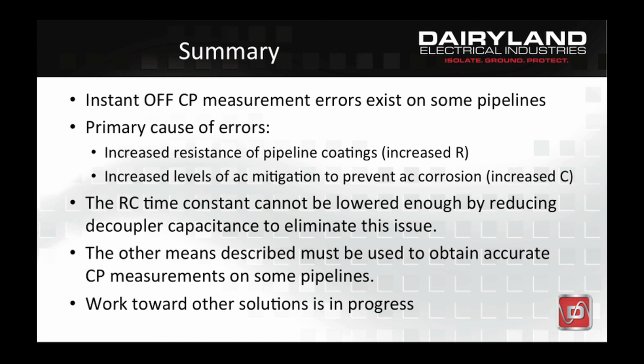It is now known that instant off potential measurement errors exist on some decoupled pipelines, and the reasons for those errors are now understood. These measuring errors were brought to light due to more pipelines in service with higher resistance coatings and increased levels of AC mitigation to prevent AC corrosion, which generally involves more decouplers along a pipeline. These two factors increase the RC time constant of the pipeline circuit, which can adversely affect instant off potential measurements. Further field testing by Dairyland indicates that the decoupler capacitance cannot be reduced to a low enough value to eliminate this measuring issue on many pipelines where this measuring error exists.